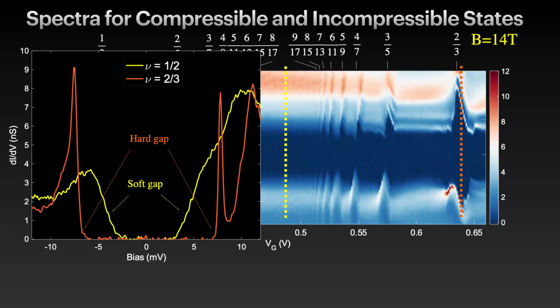So it turns out that this was anticipated by Jain, another Jain, who thinks that in this process an electron goes in, and in the Laughlin state you have 3 quasi-particles. They can make a bound state, and this bound state of the 3 quasi-particles looks a lot like an electron. And this overlap of an electron to this bound state is a way for you to add an electron to the system. So this peak may be a breaking of an electron into 3 quasi-particles, which would be quite exciting if we could study it in more detail. So all of the peaks have such an explanation.